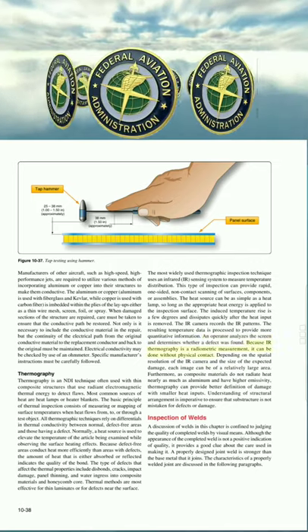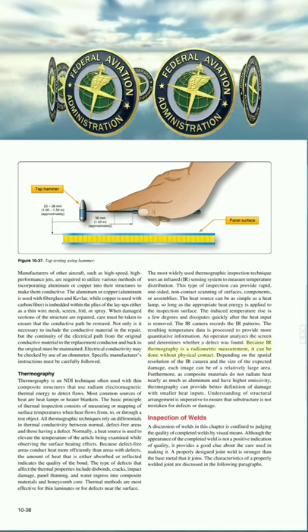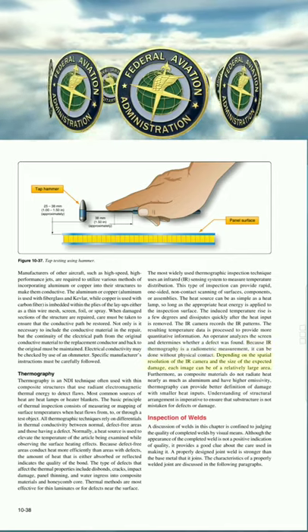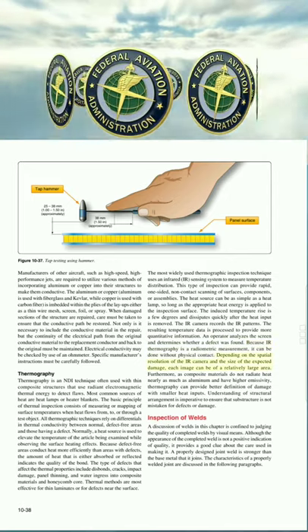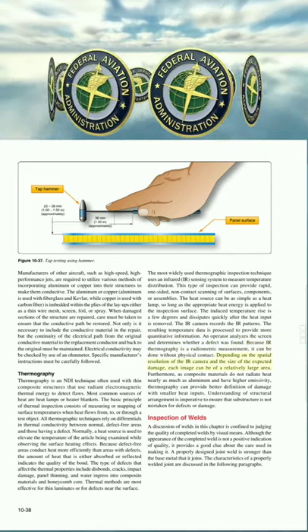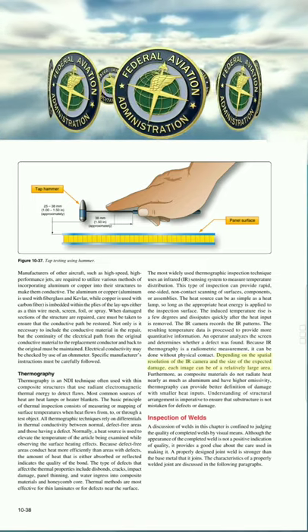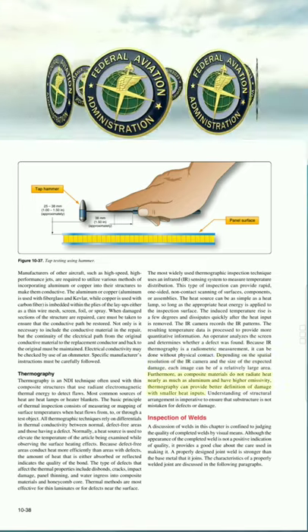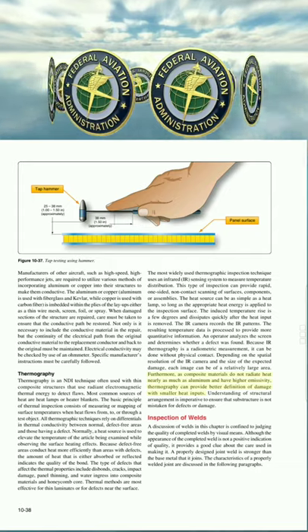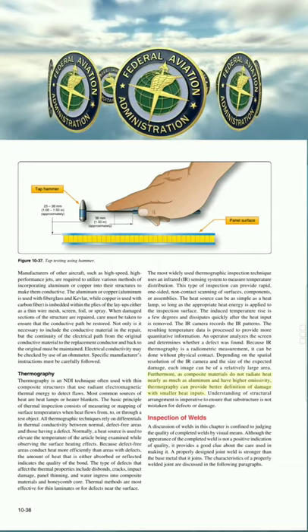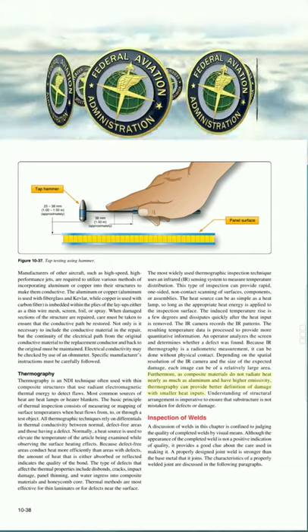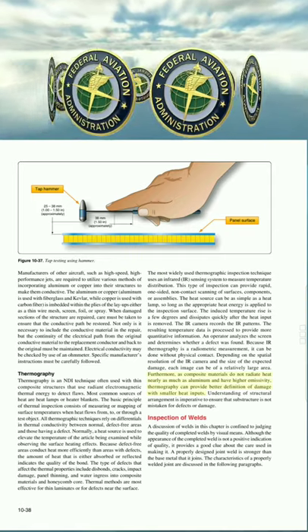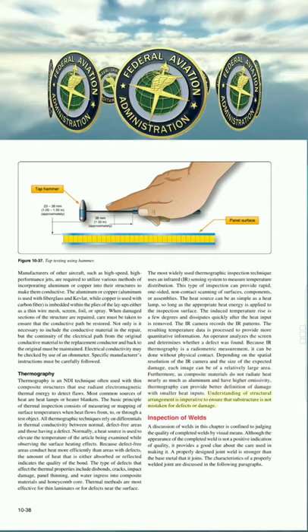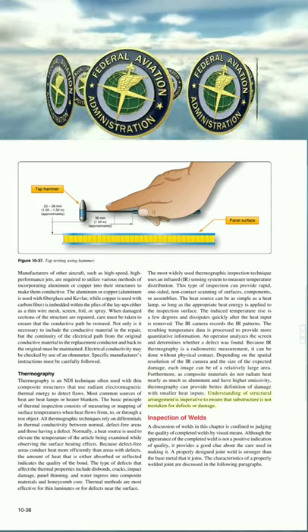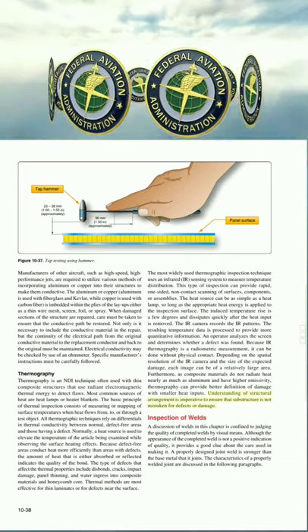Because IR thermography is a radiometric measurement, it can be done without physical contact. Depending on the spatial resolution of the IR camera and the size of the expected damage, each image can be of a relatively large area. Furthermore, as composite materials do not radiate heat nearly as much as aluminum and have higher emissivity, thermography can provide better definition of damage with smaller heat inputs. Understanding of structural arrangement is imperative to ensure that substructure is not mistaken for defects or damage.